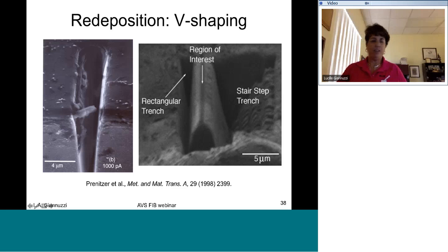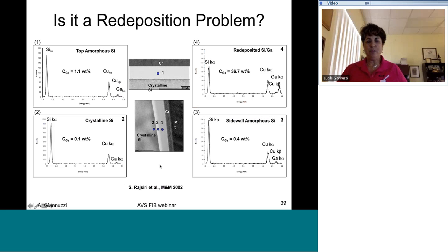That angle will vary depending upon what we're signaling. And as I mentioned before, the amount of redeposition that you see is really a function of how much gallium that you can collect or determine into your sample. So this is looking at sidewall damage in silicon. In this sidewall damage, you see the typical amorphous layer, which is noted by 3, and then you see this other darker layer denoted by 4. And if you use the EDS of that in 4, you're seeing almost 36.7% gallium.